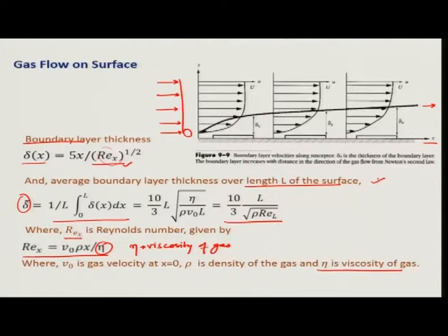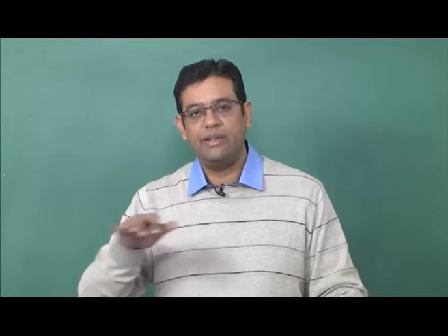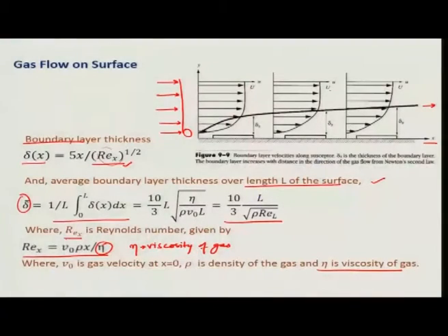So, the boundary layer is a layer of stagnant gas, right, the gas is not moving in that region. So, gases are flowing here, but not in this region, in the boundary layer there is no lateral gas flow, no convective flow. So, the only process through which the constituents which are here can reach the surface is by diffusion.